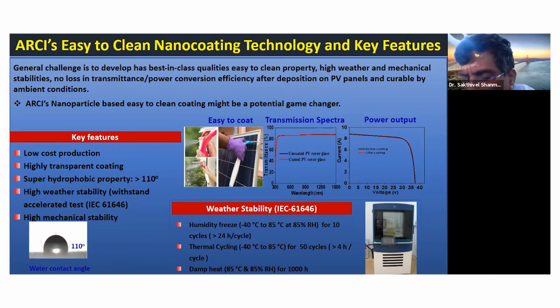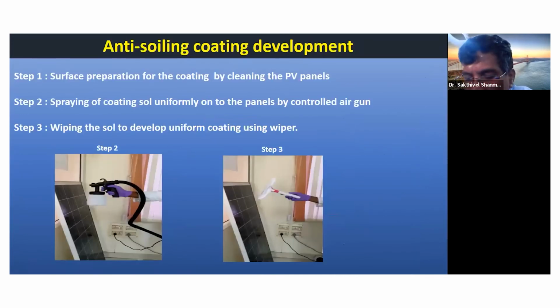So we have successfully developed 11 compositions. Out of 11, 3 were successful and passed this validation test. Among the 11, we also compared with 5 commercial ones. All the 5 commercial ones did not withstand this test, and with that positive result, we have successfully validated it.